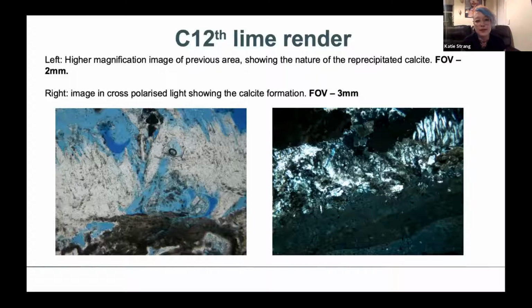So what they would have done is they were just going to strip it back, try and remove that lime wash, and then clean the surface and put a new layer of lime wash on top. So they're still doing that at the moment. It's quite a long project. As I say, with it being discovered in a basement of another building, there are access problems and things. So it'll be quite interesting to see how this develops and see if they're able to solve the problem, because sometimes when you get this reprecipitation, it's one of those things that's kind of a positive feedback. You can't actually really stop that from occurring.